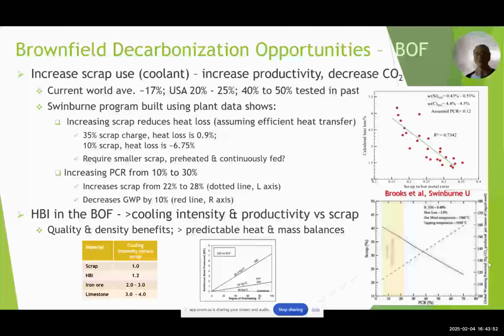With the BOF, increasing scrap use increases productivity and decreases CO2. Both the charts on the right-hand side here were put together by Swinburne University students using plant data. They show increasing scrap reduces heat loss. So for 35% scrap, you're going to have a heat loss that's less than 0.9%. If you drop down to 10%, then you're looking at a heat loss that's high at 6.75. You're going to require smaller scrap, preheated and continuously fed, probably.